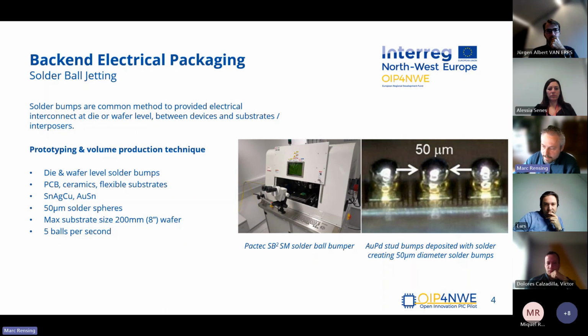And solder ball jetting is a common technique used for providing electrical connections between die and substrates. In this case, individual die and wafers, as well as PCBs and ceramic substrates, can be solder bumped using industry standard solder alloys such as tin, silver, copper, also known as SAC 305, or gold tin. Solder sphere diameters are typically about 50 microns, and the system can handle up to 200 millimeter wafers and deposit 5 balls per second. So it makes the system really suitable for prototype and small volume packaging runs.